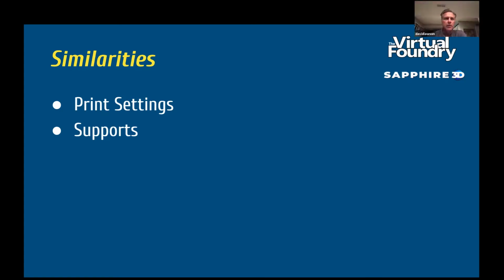Yeah, very similar. In fact, I typically will go back and forth between Filamet and just normal PLA without really changing a lot. I'll just keep my Filamet settings like Brad mentioned. 220 is what I typically use. And then it's about getting that correct flow rate. I might tweak the height of the nozzle when I do my first layer calibration. And I sort of keep it tuned for the Filamet.